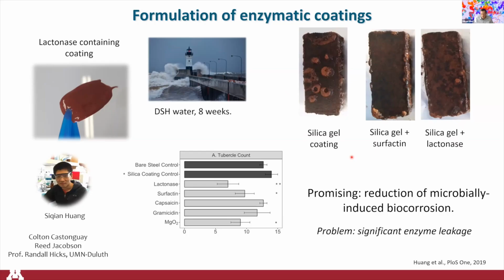And this is where we realized that this had some potential to control microbially induced biocorrosion in the context of aquatic environments. The problem was that these coatings here, these silica-based coatings, are very weak. They dissolve fairly quickly. And consequently, the enzyme is just leaking.